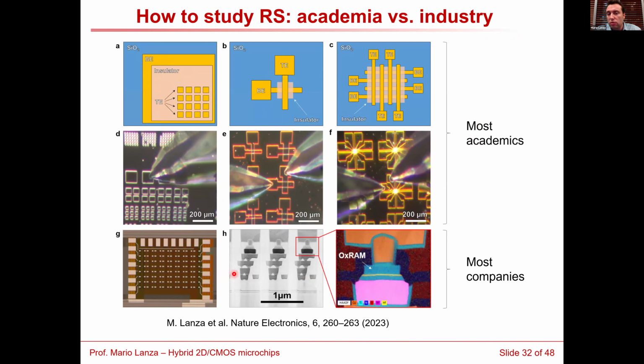What the companies do is to integrate the resistive switching material on a microchip like this. Here, if you make a cross section, you can see the front end transistors, and here in the back end of line interconnections, you can see that they have titanium nitride in the middle. They have the hafnium oxide. Okay, they have integrated the memristive material at the back end of it.